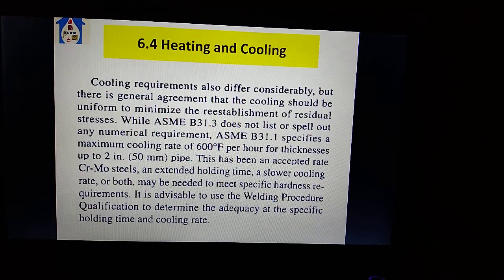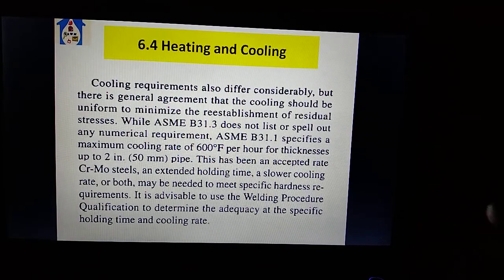This has been accepted for chromium molybdenum steel with extended holding time. A slower cooling rate, or both, may be needed to meet specific hardness requirements. It is advisable to use the welding procedure qualification to determine the adequacy of the specific holding time and cooling rate.